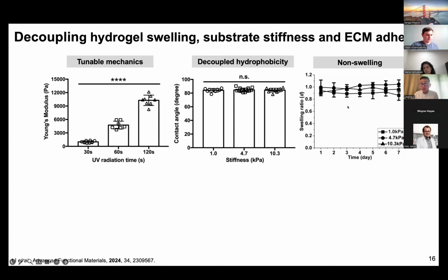So we are actually showing that these are essentially non-swelling hydrogels. You can see that we can decouple the stiffness from the non-swelling behavior. So now not only are we able to decouple the mechanical properties from the biochemical signals, but within the mechanical features, we can faithfully say that we're able to change the hydrogel stiffness, generating non-swelling hydrogels that have different stiffness.